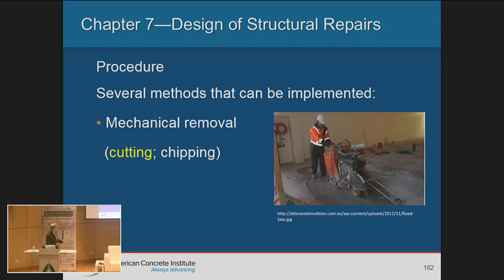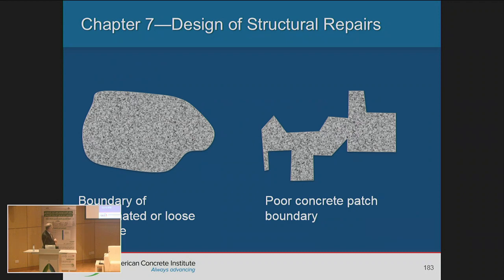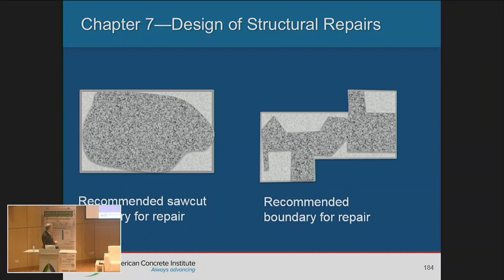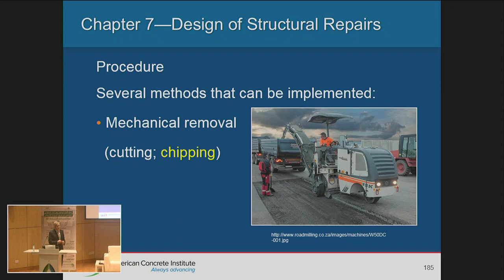The way to remove concrete is either by mechanical removal, by cutting it and removing it, as we see here. Usually that is done for small areas, like in this case where you have this shape. That shape for cutting is really not good, and the reason is that you have too many corners. Having too many corners will create weak points and the concrete may crack. That's no good. A better way of cutting the concrete would be to create square or rectangular sections for concrete removal. Or you can do chipping.